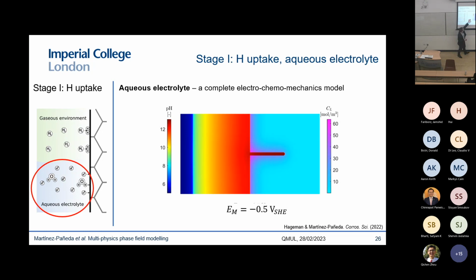So basically, you have, for example, the distribution of potential or pH within the electrolyte, and you can see how, for example, here the pH changes quite drastically from the bulk to inside of the crack. And then you can see here on the right the lattice hydrogen concentration distribution, so you can predict what is the uptake of hydrogen as a function of time, as a function of the environment, as a function of your material, and as a function of your geometry.